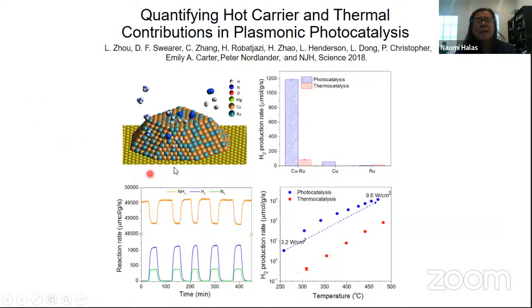So we then constructed an antenna reactor. This is a little bit different. It's basically copper. Copper is a plasmonic nanoparticle, it's a great optical antenna, and our active sites here are ruthenium. Ruthenium has a strong affinity for ammonia and for nitrogen, so this was a very good combination for an antenna reactor structure. With our copper-ruthenium nanoparticle, you can see this works really well. If we look at how the decomposition works, this is a very efficient reaction. Compared to copper, I have a very strong photocatalytic response as opposed to the thermocatalytic response for the antenna reactor.